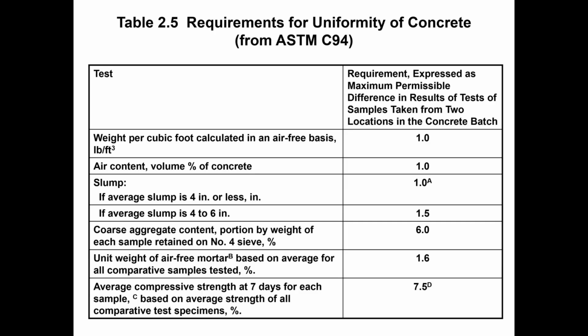And if our concrete is being produced acceptably uniformly, then the variation in those test results is going to meet these requirements. So the weight per cubic foot of our fresh concrete is going to be within 1 pound per cubic foot between our two tests. The air content is going to be within 1%. The slump is going to be within 1 inch if it's a low slump mix, or 1.5 inches if it's a medium slump mix. And it's not shown here on the table, but usually we use 2 inches if it's a higher slump mix.